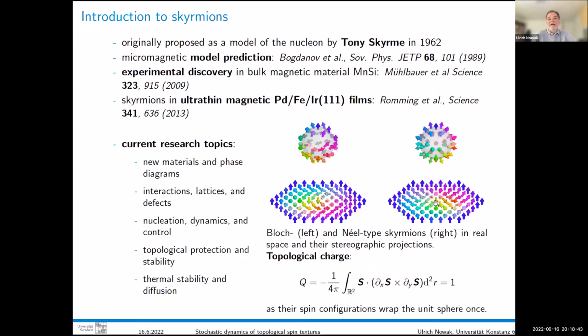Then you wind up this wall here. But on the other hand, you will have a second wall on the other side, okay, because it can only wind up in one of the directions here. So you cannot get rid of this structure. And that is called topological protection. And one can quantify this by this integral. So you can calculate this integral over this, let's say, two-dimensional structure. And in case of a skyrmion, you will get a 1. And in case of the ordered state, you will get a 0.